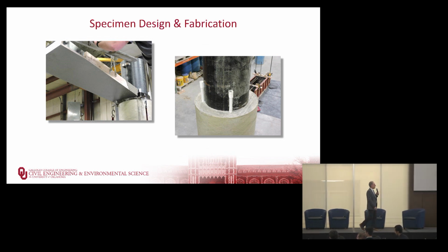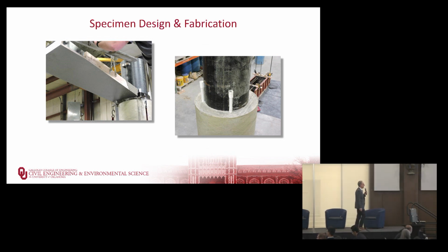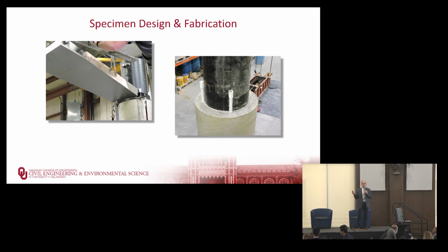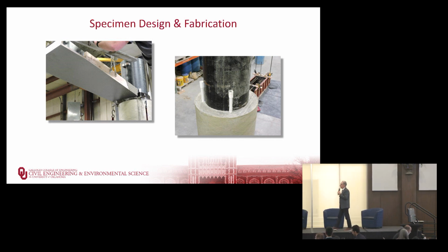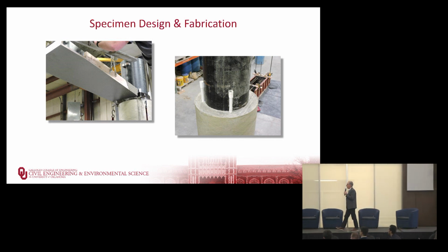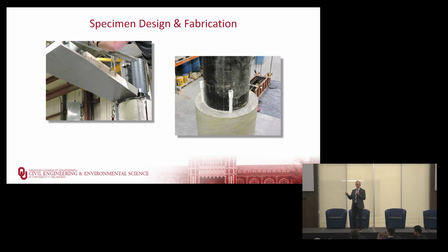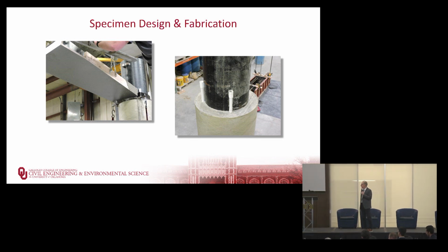This is the high strength self-consolidating concrete, compressive strength of 10 KSI. No vibration required. It filled up the space very well. Again, this is about an 8 foot tall column using a chute from our concrete bucket. Flowed very well. After our forensic analysis, there were no voids in it at all. And again, there's no reinforcing cage inside where the concrete is.